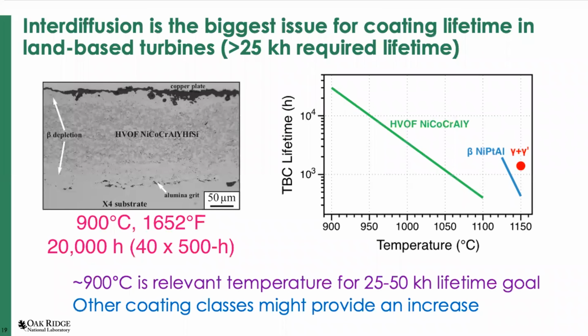And so just a couple of quick comments: if you think about coatings for superalloys, interdiffusion is the biggest issue for coating lifetime. And again, we're the Department of Energy. We're looking at land-based gas turbines. We want long lifetimes. Again, used to be the bar was 25,000 hours. Now a lot of times they're talking about 40,000, even 50,000 hour lifetimes. The only way you're going to get that is to keep the coating temperature down relatively low. You see a lot of testing in the literature at 1,000, 1,100, 1,150, 1,200 degrees C.